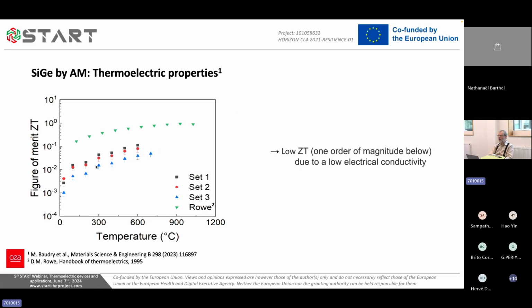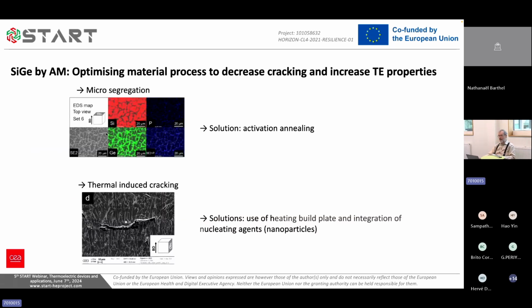So those black, red, and blue dots here are our results, whereas the state-of-the-art, those green triangles, are from the literature. So with ZT, we are one order of magnitude lower, and that's due to the poor electric conduction, mainly caused by those cracks, which we have to address. So the challenge is to improve this.